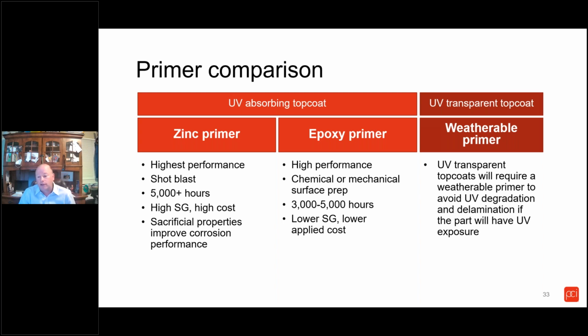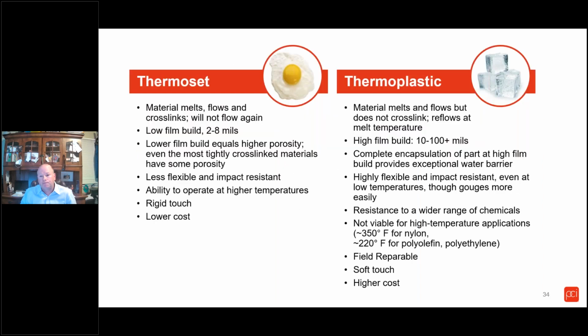If it's a UV transparent top coat, meaning it may be a weatherable coating, it won't deteriorate in the UV rays, but it also isn't stopping those UV rays from getting to the primer layer. If that's the case, you need to make sure you use a weatherable primer, otherwise that primer will chalk and cause delamination. So if you're not sure, check with your powder supplier and they'll let you know if an epoxy primer will work or if you need a weatherable primer.